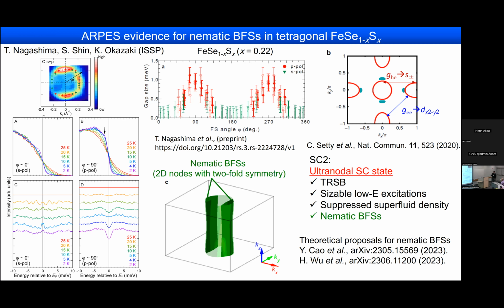So they can analyze the gap size as a function of Fermi surface angle along this line, and they find some extended angle range in which the superconducting gap does not open. So that's actually consistent with the presence of the Bogoliubov Fermi surface in this iron selenium sulfur. But we were surprised to see this result, because in the normal state it has a C4 symmetry. However, the superconducting gap structure has a strong two-fold symmetry, right? So for some reason, there is some rotational symmetry breaking occurring just below TC. But we can say that it is consistent with the presence of nematic Bogoliubov Fermi surfaces, or you can say that it's two-dimensional nodes with two-fold symmetry.